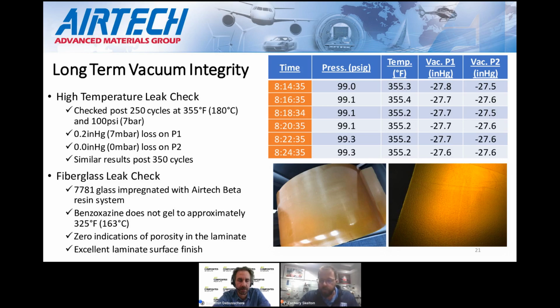We did do, I see a question from Chris Fleet there, we did do multiple pulls through the process to expedite the testing through that 350. We weren't doing a pull every cycle, but in general, we pulled a laminate every 5 cycles. So we would lay up a laminate, run 5 cycles overnight, and then the next day repeat the process. Okay, thanks.